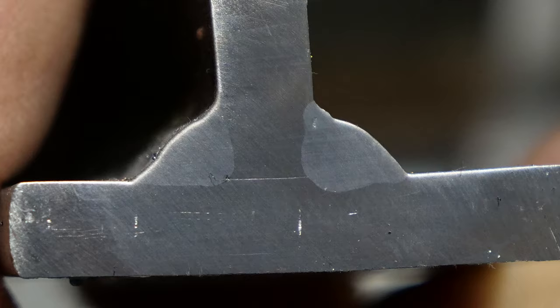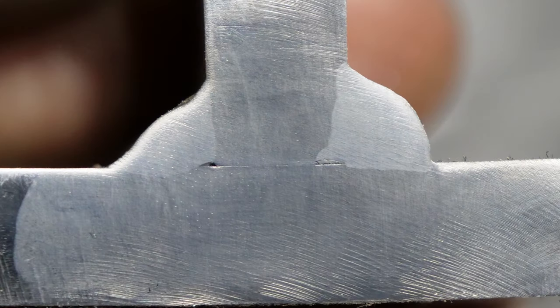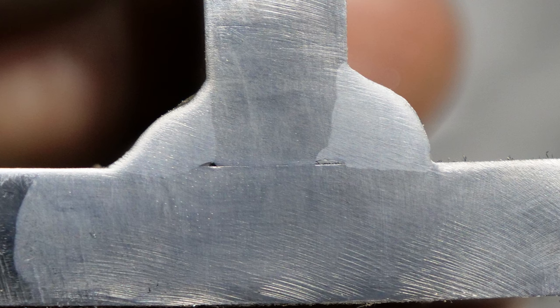Here we have thicker plate than the previous. Short arc MIG is on the left, flux core's on the right. Right away we see something a little bit different than the previous test: the flux core wire on the right has less root fusion. There's a couple reasons for this. One, I was kind of an idiot and I was doing a very small circle movement on the flux core wire weld. I thought it might help it because flux core tends to bite in the root no matter what.